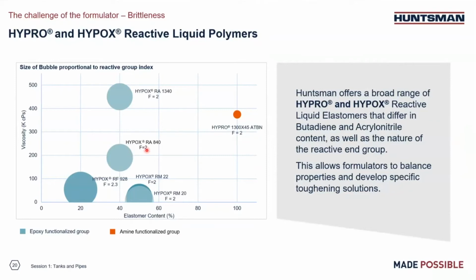We also have different epoxy-based HYPOX tougheners you can choose from. For example, we have HYPOX RM22 and HYPOX RM20. They are all low viscosity, if you want to try some low viscosity tougheners. And if you are looking for high functionality, we have HYPOX RF928, which has a functionality of about 2.3. This is based on a bisphenol F type epoxy resin, so it can have better chemical resistance. We also have other different viscosities you can choose to meet your end applications.